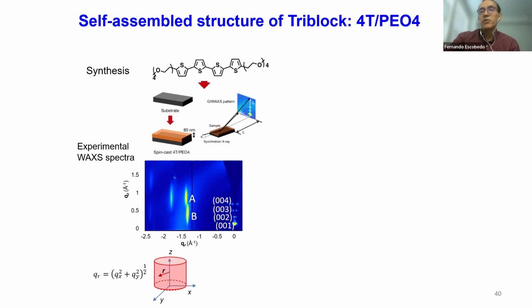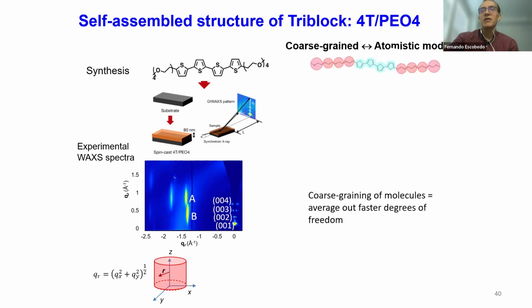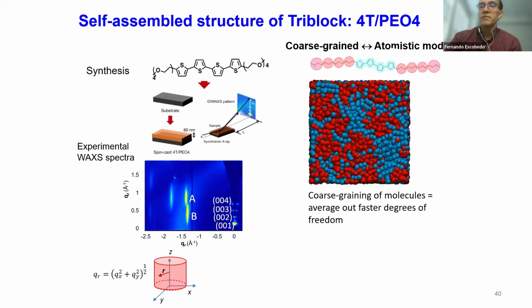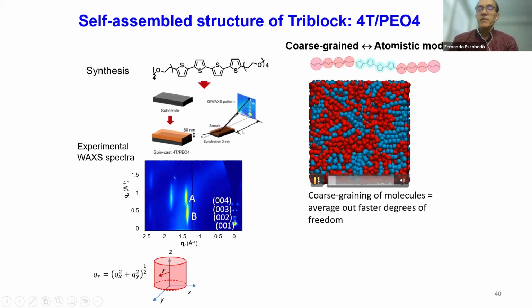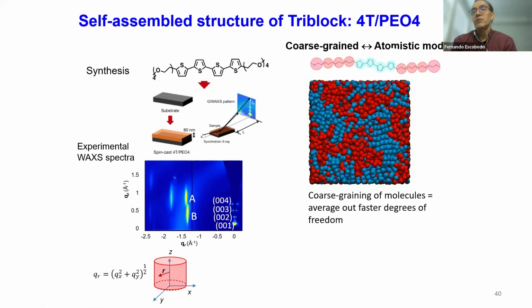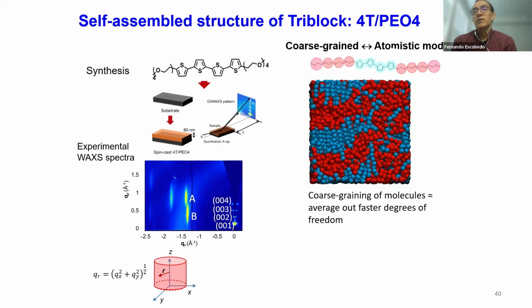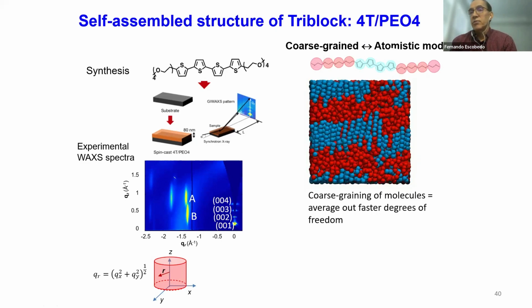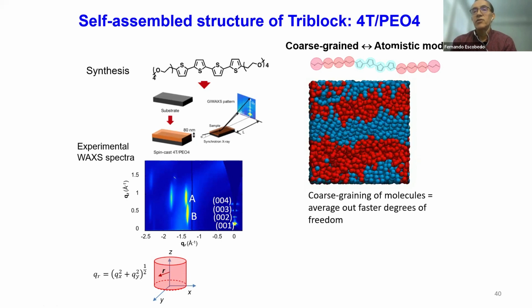Now, as far as the modeling, we thought that, well, it seems like a simple enough chemistry. We can use an atomistic model to simulate this, but it turns out that the atomistic model wouldn't assemble into this lamellar phase. It was taking a long time, and it was very, very sluggish. So what we decided was to first coarse-grain the atomistic system so that we can have a faster simulation. This coarse-grained simulation was able to assemble into this expected lamellar phase in a reasonable time and investment of computer resources.